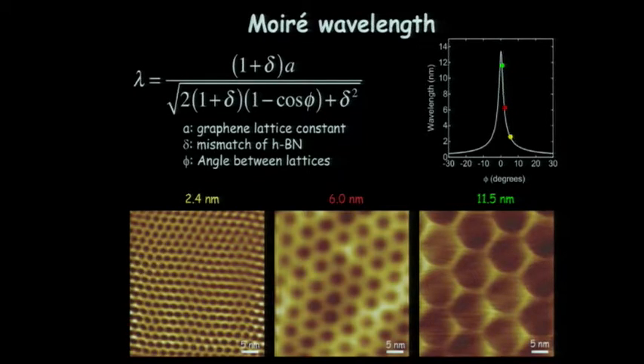It depends only on 2 parameters. One is delta, which is the lattice mismatch between the graphene and the boron nitride. And the other is phi here, the twist angle between them. So we have no control, essentially, over delta. Right? The 2 lattices are what they are. But we can control phi. And just by changing that, we get these different Moiré patterns.